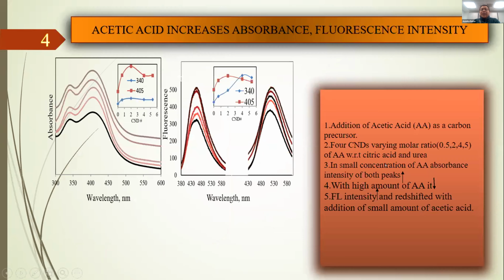To investigate the chemical genesis of the second peak at 405 nanometers, we added acetic acid as a carbon source precursor. We also prepared 4 different kinds of CNDs by varying the molar ratio of acetic acid with respect to citric acid and urea.